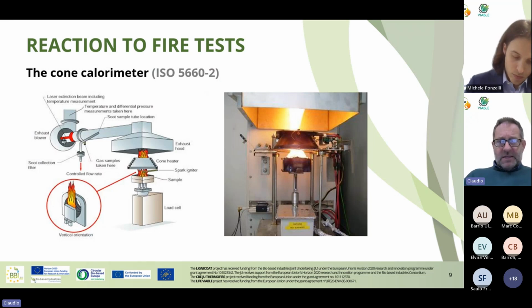The cone calorimeter is a fantastic tool for fire scientists because it allows to examine how the fire grows in very controlled conditions. In particular, this is the cone itself, and the name comes from the fact that you have a kind of heater, an electric heater in the shape of a cone, and this is giving a very uniform heat flow to the surface. So you can burn a sample, you can extract smokes in the process, you analyze the smokes. Generally, there is no temperature measurement here, so what you measure is not the real heat flux, but it's the theoretical heat developed by fire, calculated from chemical analysis.